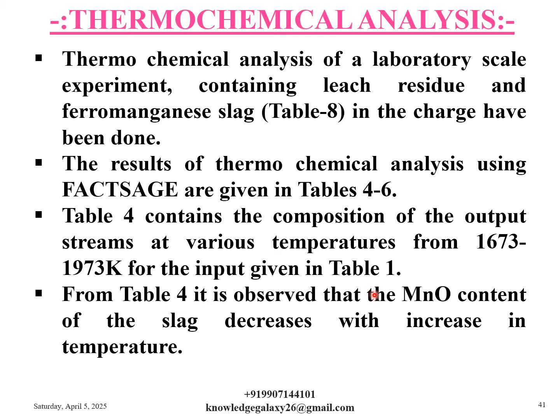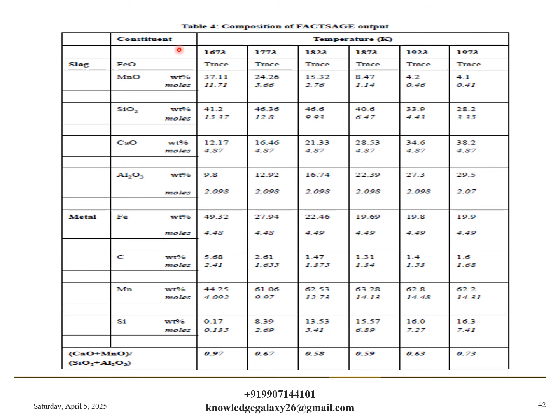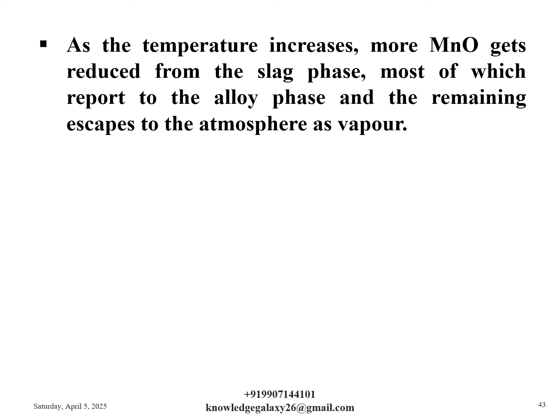From table 4, it is observed that the MnO content of the slag decreases with increase in temperature. This is quite expected. I hope I don't have to explain it much. So this is table 4, which gives the compositions of the FactSage output. As usual, you can pause the video and observe the content of the table very carefully. As the temperature increases, more MnO gets reduced from the slag phase, most of which reports to the alloy phase, and the remaining escapes to the atmosphere as vapor.